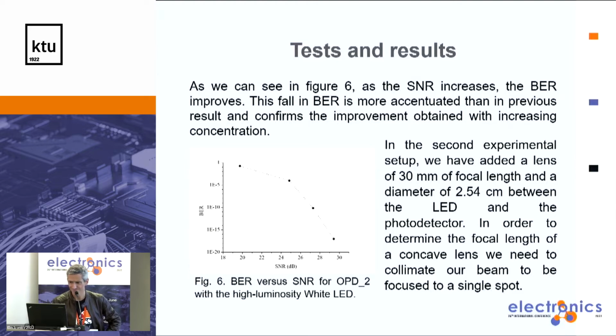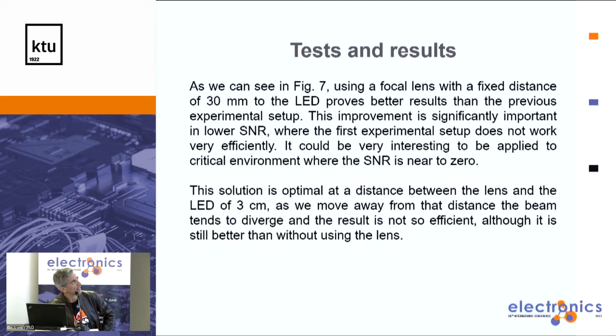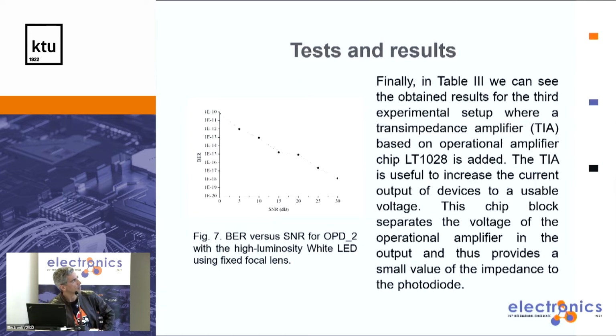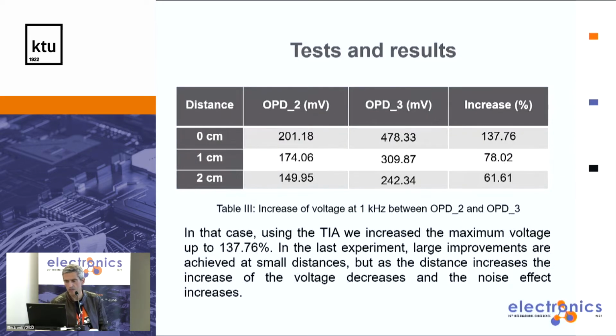The second configuration is adding a focal length, and in that case, we can obtain an improvement at lower SNR. It's important that we need to put the lens at 3 centimeters to collimate the beam. So in that case, the results are very interesting. And finally, in table 3, we can see the obtained results for the third experiment using a transimpedance amplifier. This amplifier permits us to convert the current output of the device to a usable voltage. In our case, we can obtain good results when you have small distances.